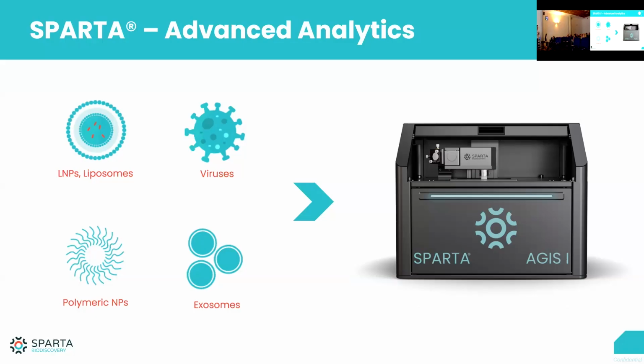And what we saw was a big gap here in the types of analysis that could be provided. There are lots of techniques that can look at the size of these particles, but almost nothing that can really look at the composition of these particles, apart from very established techniques like HPLC-MS and so on, where you break up all these components and then look at the slurry. Whilst that gives you, of course, the composition that the bulk of these particles are made of, we're losing a lot of information that's very relevant, namely the variation between these particles in terms of the compositional profile. Because all these particles, however hard you might try with your formulation, are not created equally. There's a lot of variability there, and that's exactly what we want to measure.